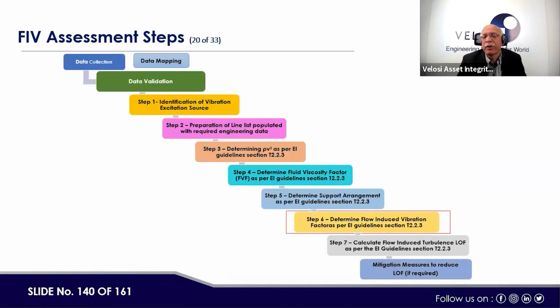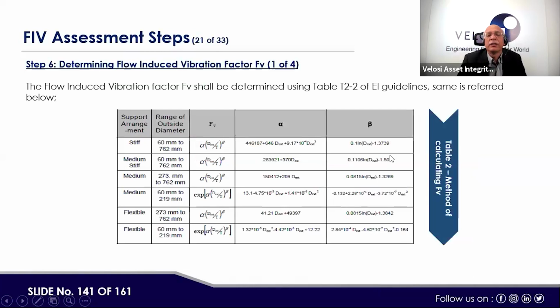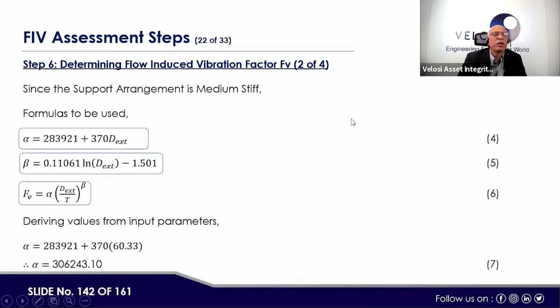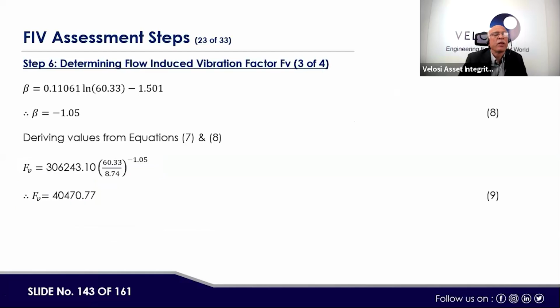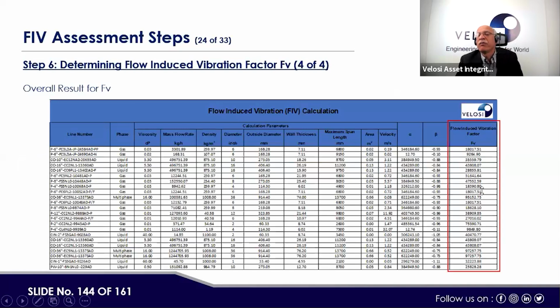Then the next step is to determine flow induced vibration factors as per EI guideline section T2.2.3. Here, when we come to determine the flow induced vibration factor FV, this is the formula; we have to calculate alpha and beta, which are calculated as in this example. These calculations are done for each pipeline, basically each piping system. The end result of the FV calculation is 40,470, and this FV factor is calculated for each line in the Excel spreadsheet.